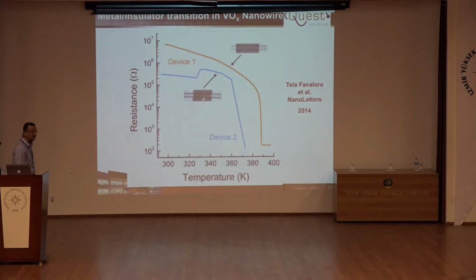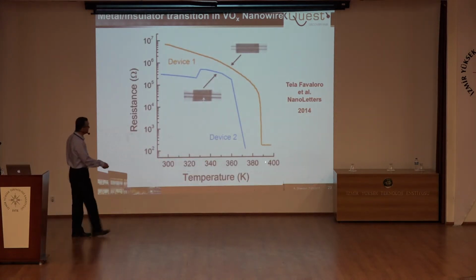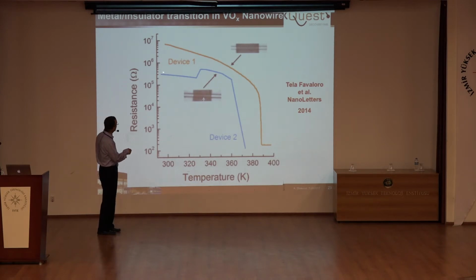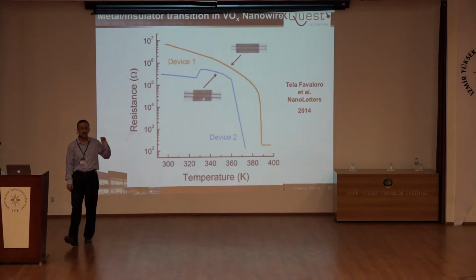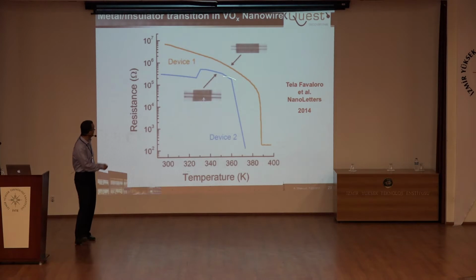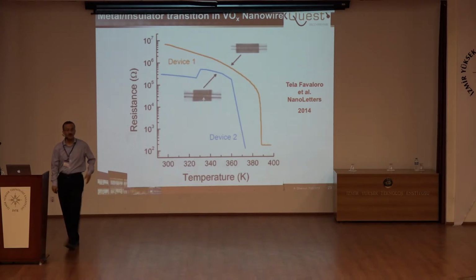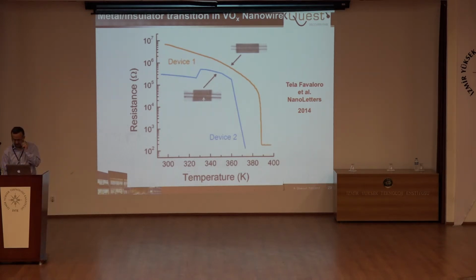Again, if you do the end-to-end measurements, the resistance versus temperature of these beams, you see that they go from high resistance to low resistance in a small temperature range. So you know it's a phase change material. You go from a metal to insulator over a small temperature range. So here you have all domains that are resistive. Here you have all domains that are metallic. And in between, you have multi-domains, and that's how we can see what happens inside the device.